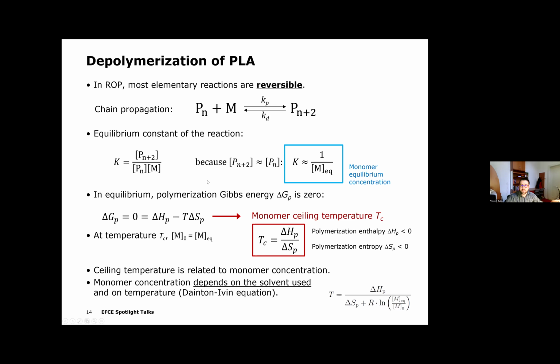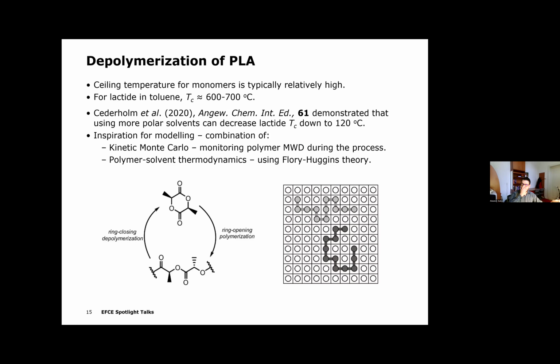And the ceiling temperature is related to the concentration of monomer. And the monomer concentration depends not only on the temperature following this Dainton-Ivin equation, but also, since it is a molar concentration, it depends on the solvent that is used. And that is basically the most important idea of this work, which doesn't come from our head.